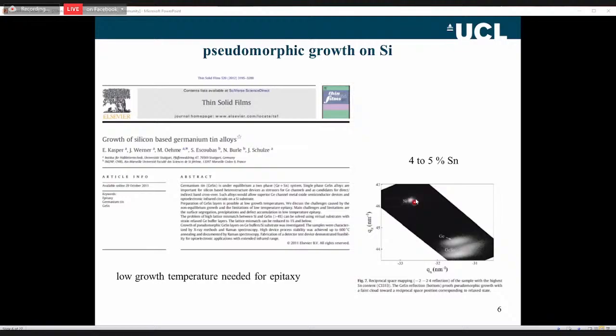This is an X-ray measurement. This is the silicon from the substrate. You can see the germanium is shifted here because germanium has a different lattice constant. It's relaxed. Germanium-tin is coherent with the germanium layer, and the way that this problem of epitaxy was overcome was to use a very low growth temperature. When you grow these materials at lower temperature, you can incorporate tin into the lattice, but you tend to get other things like impurities, carbon, oxygen, and the like, that wouldn't normally get incorporated at higher temperature.